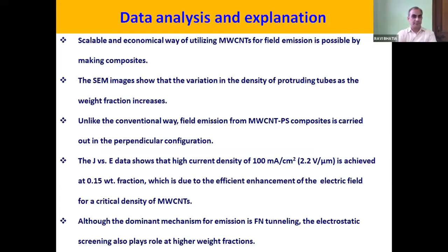So let me just take the important comment here. J versus E data shows that 100 milliamp per centimeter square can be obtained with an application of 2.2 volt per micron. And because at this particular value of weight fraction the protrusions are not screened by the presence of other protrusions, this is the optimized number which we get in the case of the 15 weight percent sample. But this work needs to be verified by other groups as well, and theoretical modeling should be done for the validation of this work.